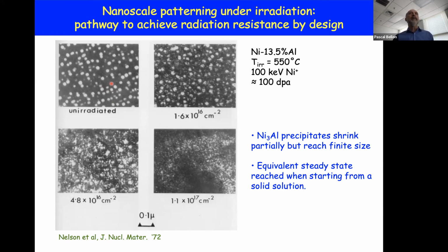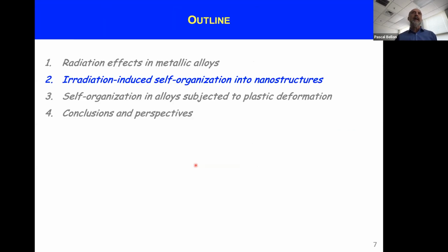And if you irradiate this material at the right temperature, that is not too high, not too low, the precipitates will tend to decrease over time due to the irradiation damage and the mixing that I mentioned earlier on. But as you increase the dose, and this is going from top right to bottom left to bottom right, the microstructure seems to reach a steady state microstructure that is independent of the initial state. So here they started this set of experiments with pre-existing gamma prime precipitates. If you were to start from a solid solution, they reported that they obtained the same microstructure. And so it seems that under those conditions, under radiation, the precipitates reach a finite but stable steady state size. And this is what I'm going to now detail in this section.